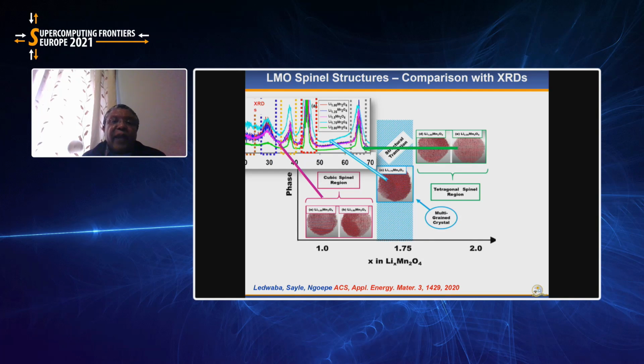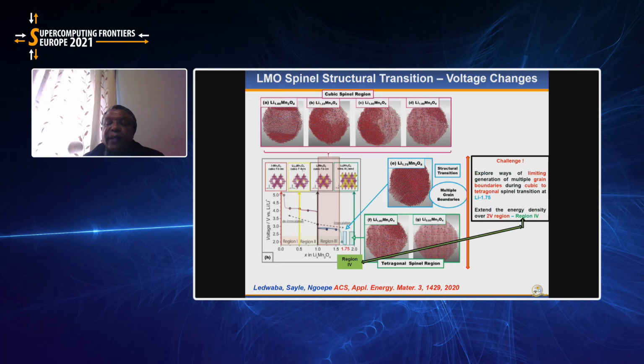We can see from this picture that this multi-grained phase corresponds to X-ray patterns that are very broad, whereas the other two extreme regions consist of patterns that are very narrow, which means that they are highly crystalline. We also see that the spinel phase corresponds to a voltage of around 3 volts. That voltage drops when you go to 1.75, to this phase, and then when you go over to the tetragonal phase, it remains low.